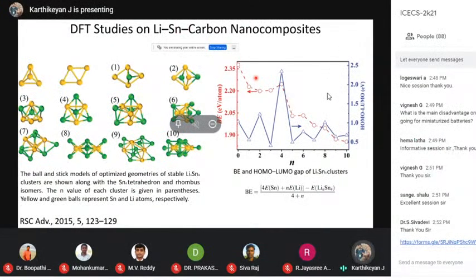So the mechanism, what is happening inside this material when you add lithium in the anode compartment, especially during the charging cycle. You are actually adding lithium in the anode compartment. So what is happening exactly when you mix lithium with the tin nanoparticles? So we are going to use density functional theory for this. As I told you, it is really computationally heavy. If I take a nanometer size tin nanoparticle and put it inside a CNT, and study all this lithiation, it is really going to be a challenging task.